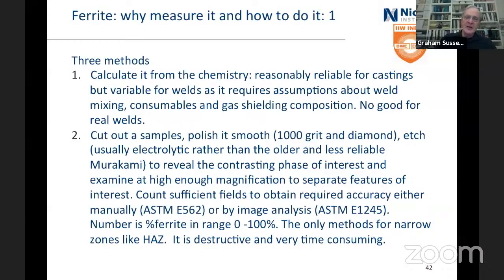All right, so cut out some samples. It's destructive, so you can't do it on site. Well, all right, let's keep going. Polish it smooth, 1000 grit and diamond, etch it, and it's usually electrolytic. Some of us old people used Murakami, and I always found trouble with that, but still the electrolytics work very well. And you get nice contrasting phases, and examine it at high enough magnification so you can separate out the features you're interested in.